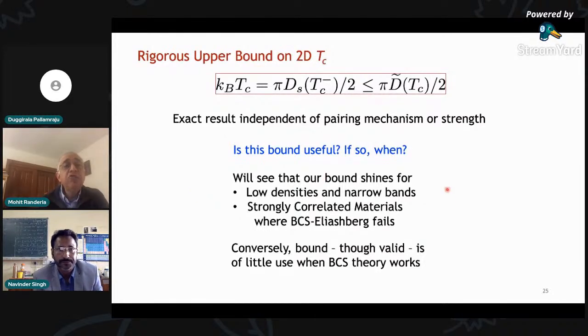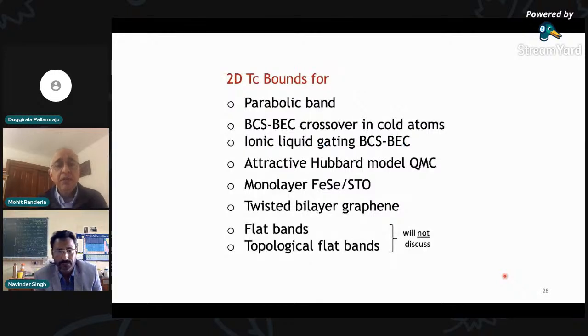We will see that this bound shines when you have low densities and narrow bands, and particularly when you have very strongly correlated materials where the BCS-Eliashberg framework fails. Conversely, there are situations like aluminum or lead, where BCS theory works extraordinarily beautifully. Our bound is valid because it's a general bound, but it will also be shown to be useless, meaning it will be humongously large. Okay? So these are lessons that we will learn as we proceed. Of course, a formal bound, even if exact, is only as good as what you learn from it. So we have tested it against a wide variety of systems: experiments, quantum Monte Carlo simulations, model calculations. I'm certainly not going to discuss the flat bands and topological flat bands, but let me try to give you a flavor for how this bound works.